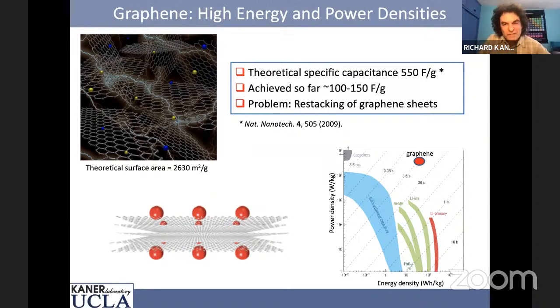And of course, the problem is restacking. So a single sheet of graphene has a surface area of 2,630 meters squared per gram. But that means that you can access both sides of each sheet. And so if you put 2 layers together, you lose the bottom half of the top sheet and the top half of the bottom sheet, and the surface area per gram drops from 2,600 to 1,300. If you had 3 layers, it would drop by 1/3, or 4 layers by 1/4. And so if you look at this, if you get 100 or 150 farads per gram, it simply means that on average, you have 4 layers of graphene. And so when you build a real device and try to scale this up, you get much less than the theory. And so we've done a bit better, and I'll show you why.